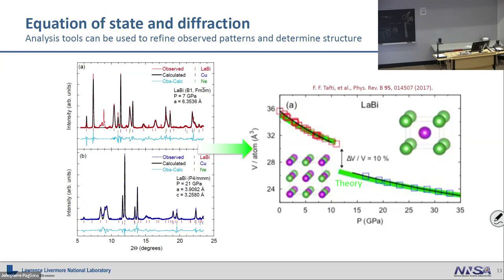One of the important things is calibrating this, because we are looking at something, this is probably done at about 25 kilovolts. That's generally where we do these things. If you're used to lab sources, you're out at 90 or 100 degrees typically with your diffraction patterns. Because we're at high energy, that scattering cone shrinks and narrows in, so everything happens down here, more like in 25 2 theta. So if you were on a lab source, like a copper source, you don't even get a diffraction peak until out here. And what that really drives you to is having very high resolution on your detectors and understanding your resolution and calibrating that resolution with something like cerium dioxide or some other standard at ambient pressure.